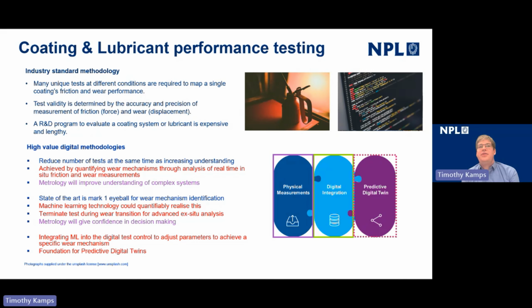Conventionally, we look at a wear scar on the surface under an optical microscope, and experienced scientists will classify the wear mechanisms that went on during the experiment and make inferences on quite long time bases. We're looking at friction signals. So it may be looking at the characteristic behavior of the friction force over tens of minutes or even hours, and then looking in closer detail at highly localized transients and trying to infer points in the experiment where the mechanisms changed.